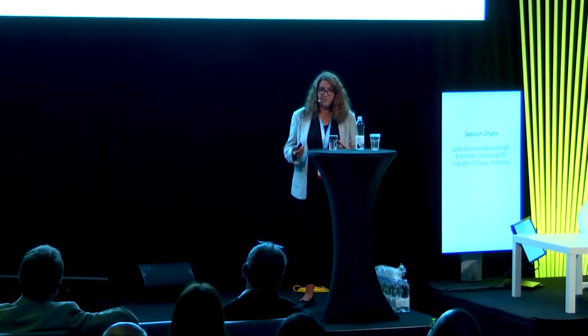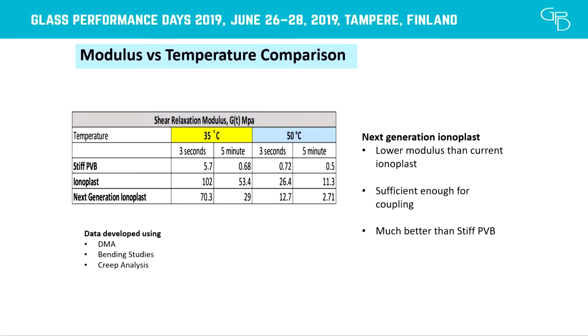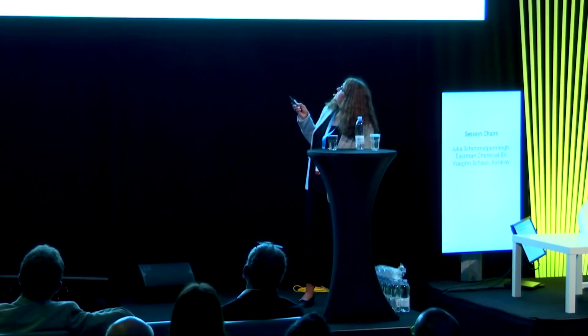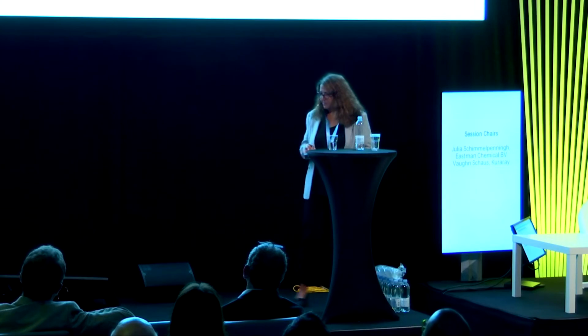So if you look at modulus versus temperature, this data was collected using 3 different methods. We used DMA, bending studies, and creep analysis. I'm not going to get into the whole discussion about methodology because that's something that's been a big debate lately, that we need to come to a common standard test method for developing these types of data. But for now, this is what we have done, and you can see that I have stiff PVB here as a benchmark, and this is our current Ionoplast and the next generation. So you can see it is lower. You do have lower modulus in the next generation, but we believe it's sufficient for coupling, and it's much better than stiff PVB.